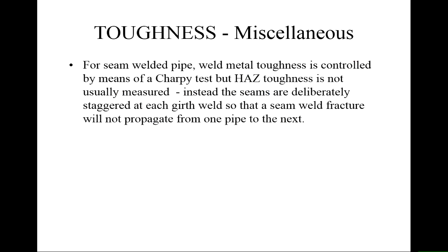So, for seam welded pipe, weld metal toughness is controlled by means of a Charpy test. Now, of course, the weld, as if you didn't already know, we'll talk about later, consists of the weld metal that's deposited, and that's the thing that tends to be tested with Charpy. But either side of the weld, the steel has gone through a heat cycle which changes its microstructure, and these things are called heat-affected zones.